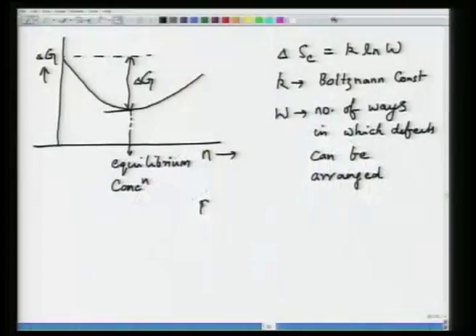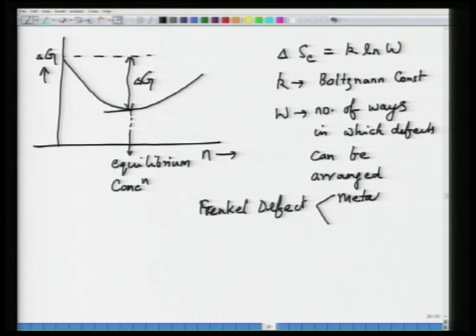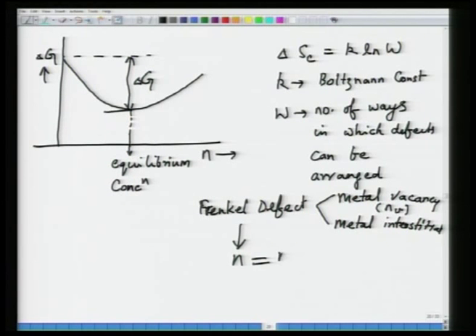Sorry, on the atomic sites or in the lattice. So, let us say now when you form these Frenkel defects. A Frenkel defect would mean you have a metal vacancy and a metal interstitial. Now, let us say the total number of defects is equal to n. This is going to be equal to the number of vacancies, Nv, and the number of interstitials, Ni. So, just by looking at the defect reaction itself, this is very simple. The number of Frenkel defect pairs n is equal to the number of metal vacancies and the number of metal interstitials.